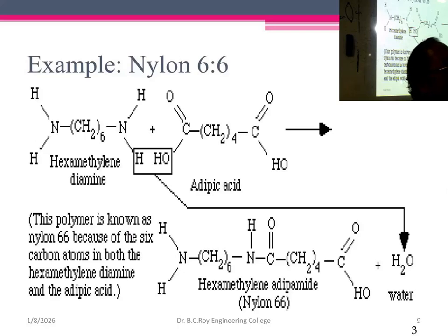Enough. Because they are already hot, the reaction will also be very good, and whatever water is produced will be evaporated, and your polymerization will immediately start. And if the polymerization has started, it is becoming highly viscous. Stirring will also be difficult. Got it? So uniformity will be difficult. Making it uniform will be difficult. So that's why preheating is better compared to post-heating.